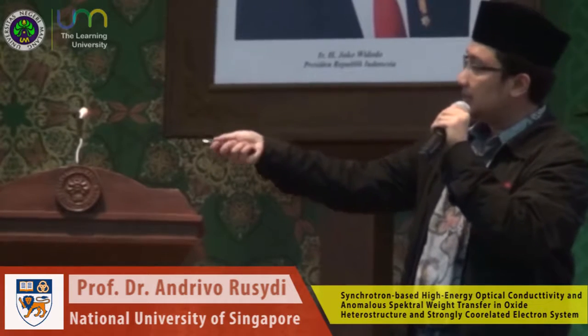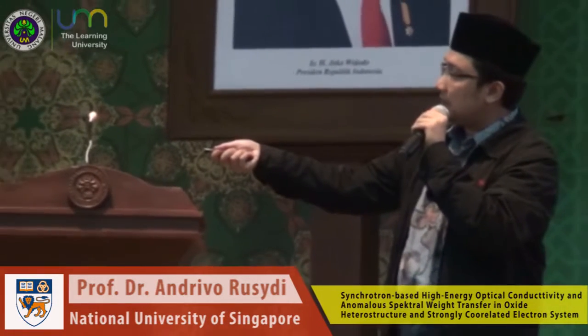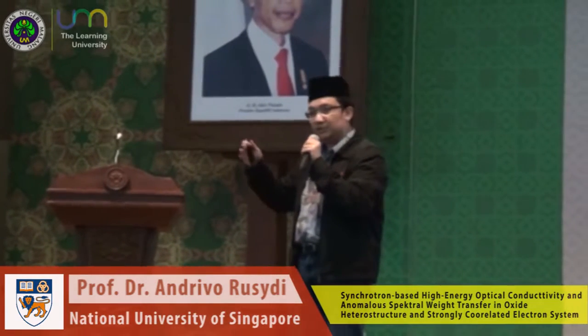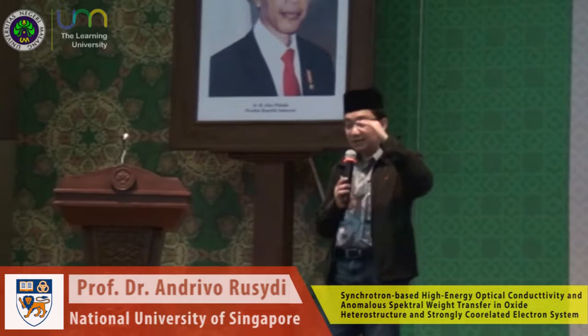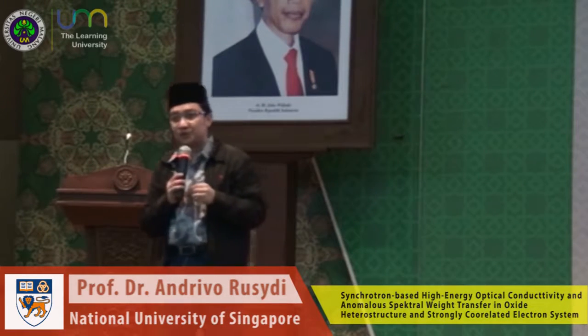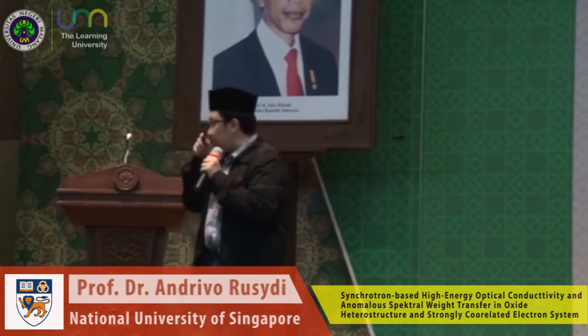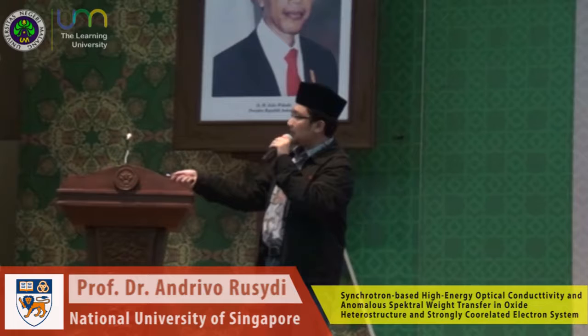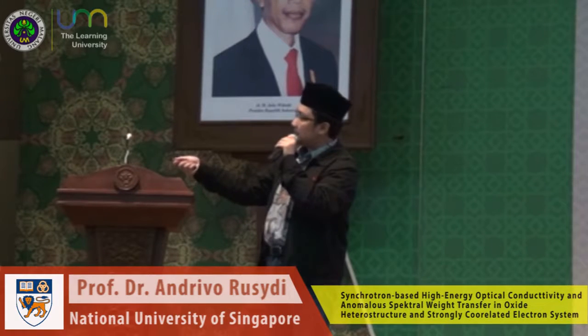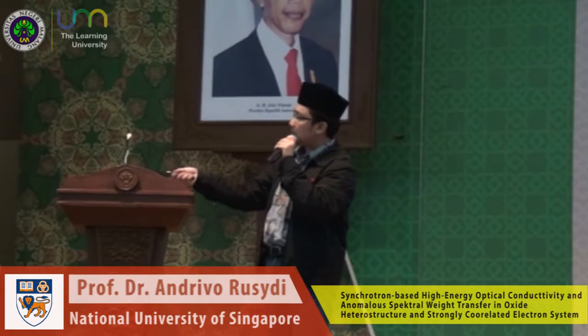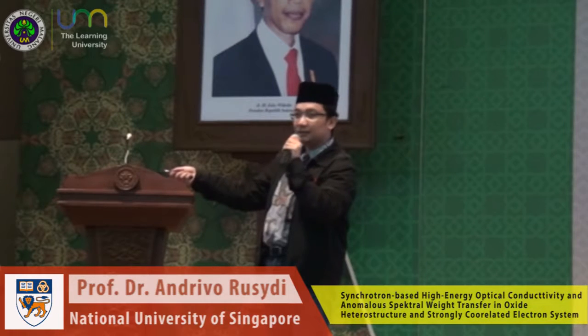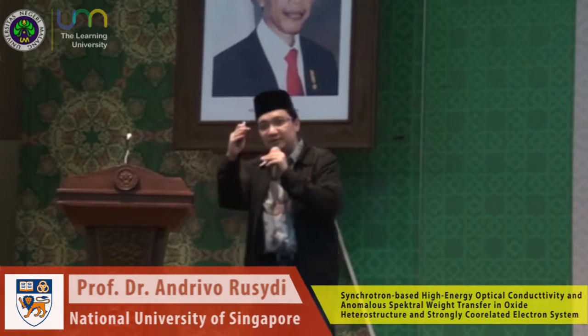This is the number of unit cells of lanthanum aluminate, the polar material, as a function of the sheet conductivity. Zero means there is no polar LAO. Then they increase to 1 unit cell, 2, 3, 4, and so on. One unit cell is about 4 to 5 angstrom, much less than a nanometer. At zero LAO, they got zero conductivity. They increase to 2 and 3 unit cells, they remain insulator, because everything remains zero.